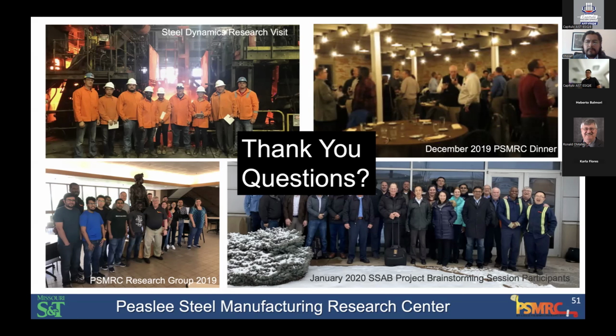The hydrogen influence on the inclusions is actually a pretty interesting question. And I've not studied the reduction potential of hydrogen in those environments, but I've not seen much evidence that at steelmaking temperatures it has a big impact. Because, in the end, hydrogen has a limited solubility in the steel at steelmaking temperatures, right? And you probably will never get above 14 ppm without it outgassing anyway. So whether that's enough to do some reduction, I suspect it's completely benign if you're aluminum killing. It might have some impact on FeO emulsion inclusions or possibly even manganese silicates. And I'd have to investigate that further.